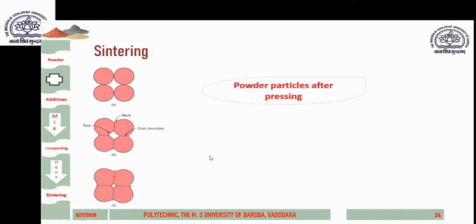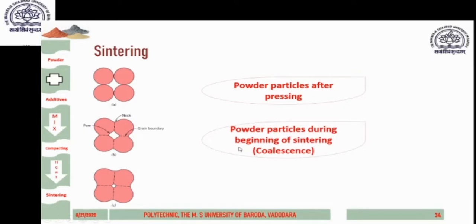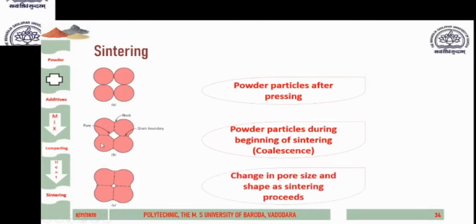Okay, so just look at this. What are these? Powder particles after pressing, then powder particles during the beginning of sintering, that is, coalescence is occurring. That means different areas, different points which were in contact have started melting and getting associated with each other. And the third is the change in pore size. So this is your pore size, which gets reduced as the sintering process proceeds. Okay, so this is what happens when we do sintering, and it is expected to be done very nicely so that we get very good strength of the material in the metallic bonding condition, and the material can be used for performing the required function with the required physical and mechanical properties.